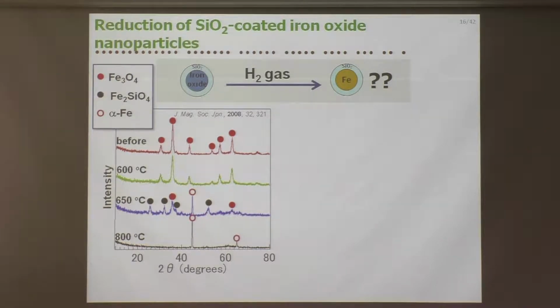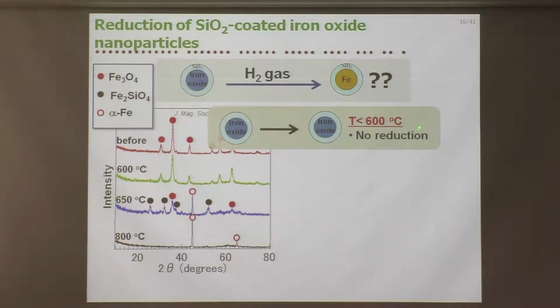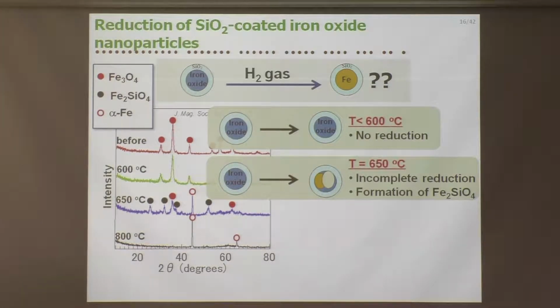Here shows the XRD patterns of the samples after hydrogen gas treatment at different temperatures. From this figure, we can see that at temperatures less than 600 degrees Celsius, no reduction occurs, so we have to increase the temperature to carry out the reduction. Second, at 650 degrees Celsius, now we can see diffraction peaks from the alpha iron phase.